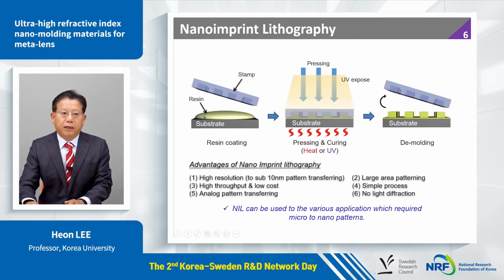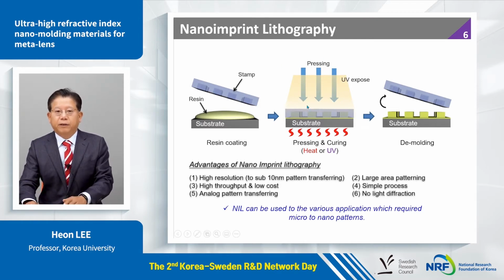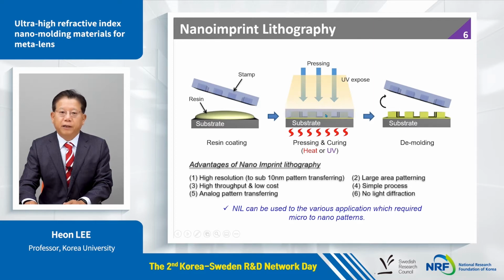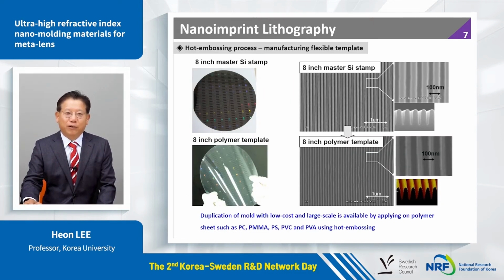So here's a substrate, and I have a resin, imprint resin, and a stamp. Stamp means the one that has some surface protrusion pattern. While pressing the substrate and the stamp, the cavity of the surface is filled with the imprint resin. During that time, we can do UV exposure or apply heat. The liquid phase resin turns into the solid phase. After that, we detach the mold, then we have a nice pattern. Because the whole process is very simple and very high resolution is available, nanoimprint lithography is the best technique to mass produce the metasurface.